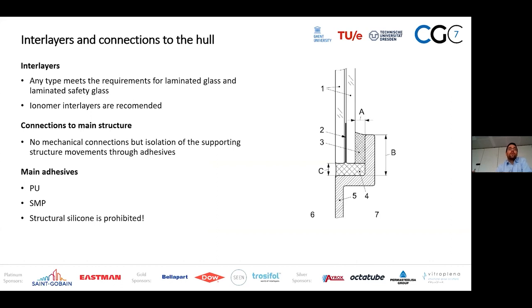One of the most important topics in yacht glass design is connections to the main structure. The main assumption here is that the glass is infinitely stiff and the structure that it connects to behind can move by a lot. This movement is accommodated by the adhesive, which is not structural silicone. In the marine industry, it is prohibited to avoid contamination of the substrate and failure of the paint. It is mainly polyurethane and silane modified polymers.